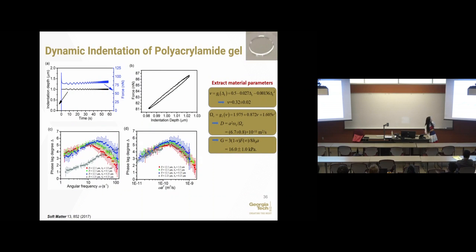This is one set of experimental results on polyacrylamide gel at small scale. We tested this: the black line is the applied displacement, and this is the measured force. This is over one cycle of loading oscillation. You can see we get this hysteresis. And for different indentation depths, you also see this peak characteristic time depends on length.